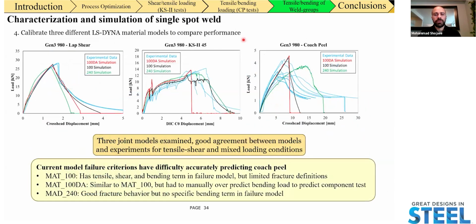And we compared the load displacement response between different single spot weld characterization tests. I'm showing the results for lap shear, KS2 at 45, and the coach peel test for Gen3 980 at the top here, for three different LS-DYNA models. Specifically, the blue lines are the experimental data points. The red is the calibrated LS-DYNA model from the MAT100DA. The black one is the MAT100, and the blue is the 240 simulation.